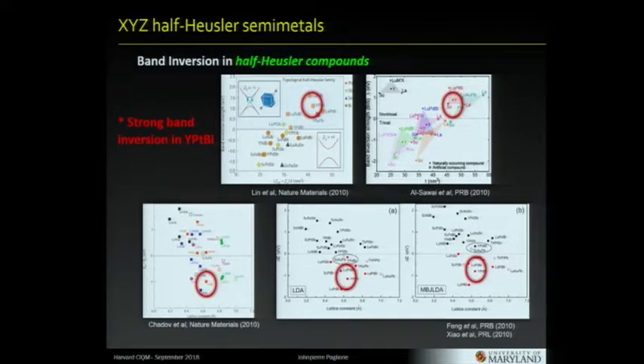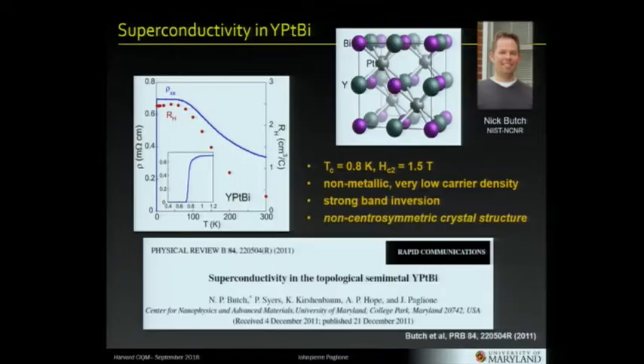Chronologically, this is the first material we studied, but I like to show it in this order because now we're looking at a platinum-bismuth series where it's a bit further off the line, and this means it has a very strong band inversion and should be a good topological insulator. So we started actually looking at yttrium platinum-bismuth. We essentially threw a dart at the dartboard and said, okay, let's start with that compound. We did some crystal growth and basic characterization, and we found that it was a superconductor, which was surprising, because it's a very non-metallic compound. It's essentially a semi-metal. The resistivity increases as you cool it down, and then below 1 Kelvin there's a superconducting transition, which we found several years ago.